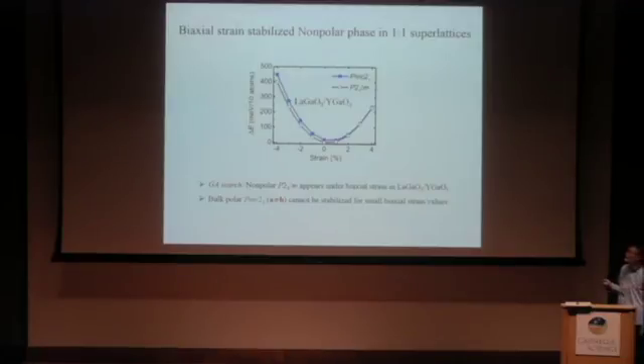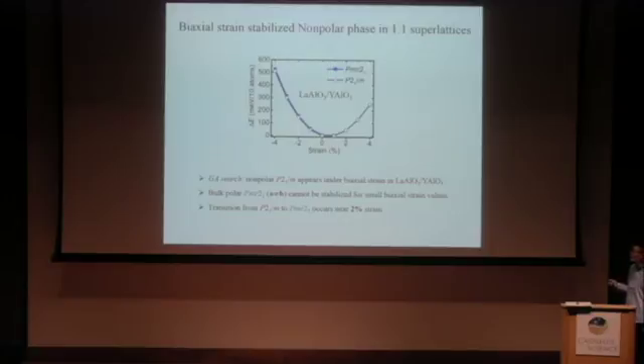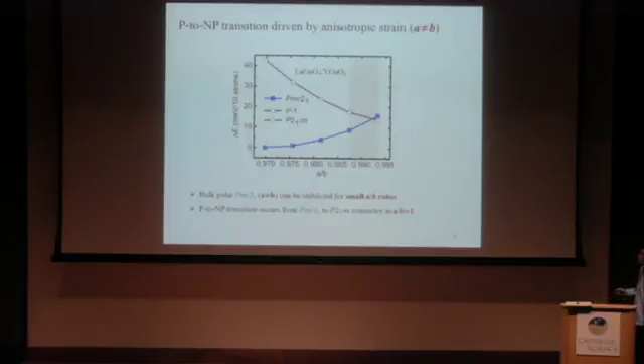We then found in the lanthanum yttrium gallium oxide the previously predicted bulk Pmc21 phase cannot be stabilized under biaxial strain, while the P21m nonpolar phase can be more stable in the whole strain range studied here. And we also found in the lanthanum yttrium aluminum oxide the P21m phase can also be stabilized up to a tensile strain at 2%. And to further elucidate the stability of the P21m phase under biaxial strain, we also investigated phase stability under the anisotropic in-plane strain. Here we found with increasing the a/b ratio, the energy of Pmc21 gradually goes up, and the energy of P21m will gradually go down, which results in a crossover at a/b approximately equal to 1.